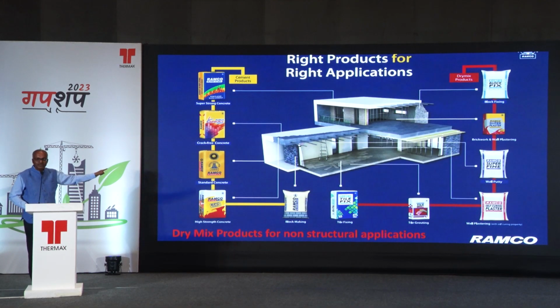So it does the work of both environment as well as being environmentally friendly. One type cannot fulfill everything. So we have, for example, something to fix tiles. We were surprised to see many of them are using cement mortar. Instead of using cement mortar, you can go in for tile adhesive, which can be 3 mm thickness. You don't have to use 8 mm. And after a few days, you will find that there is a hollow sound on the tile and it debonds and things like that. So there are tile fixes which are available.